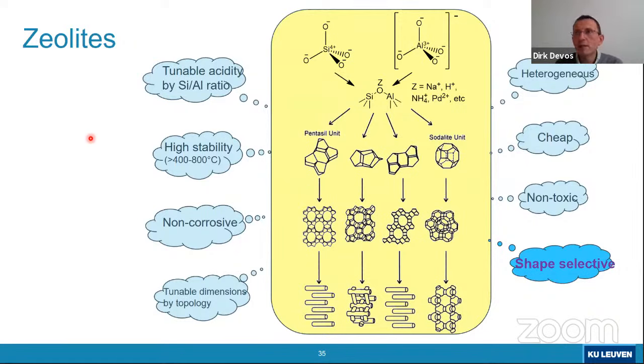Why? Because in a zeolite, you can change the number of proton sites that you have by varying typically the silicon to aluminum ratio. A zeolite is essentially SiO2, in which you replace part of the silicon by aluminum. So each time you replace a silicon by an aluminum, you get a negative charge in the lattice, which means that there can be, for instance, a proton sitting here. But actually, this can also serve as charge compensation to a catalytic cation, like, for instance, palladium. Why not? Another positive aspect of zeolites is that they are very stable. They have very well defined and tunable pore sizes, and there are like 100 or 200 different zeolite topologies known till now.